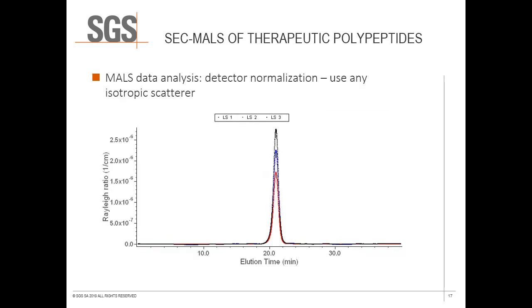It is also necessary when performing multi-angle light scattering analysis to normalize the light scattering detector response. For this correction, an isotropic scatterer is injected, which is a polymer small enough in solution to scatter light equally in all directions, less than 10 nanometers in hydrodynamic radius. If, for a given peak, light is known to scatter equally in all directions, then detector voltages should be identical at all angles. For this, we use the same 17 kilodalton PMMA used for alignment and band broadening corrections.